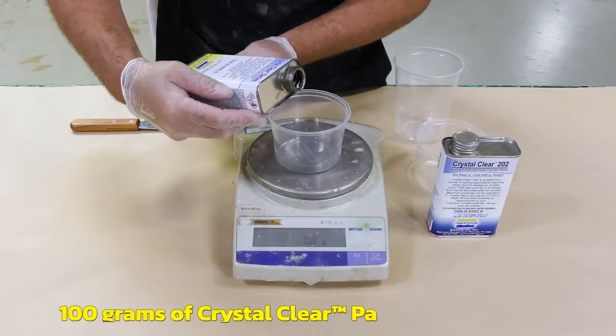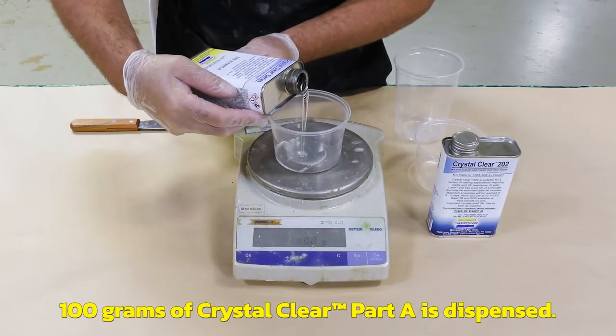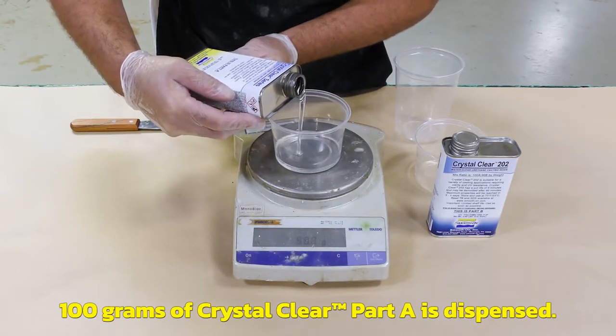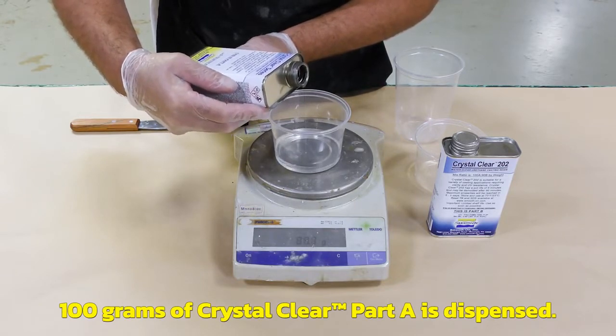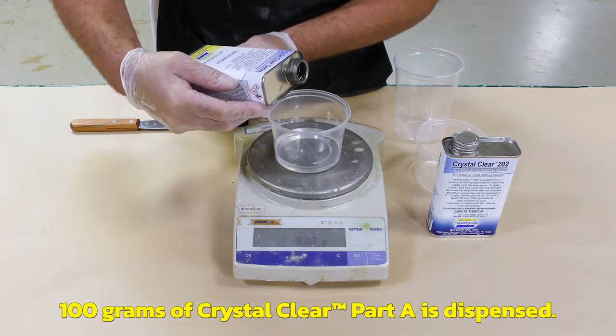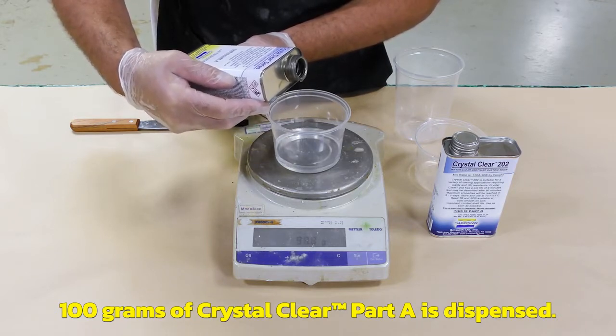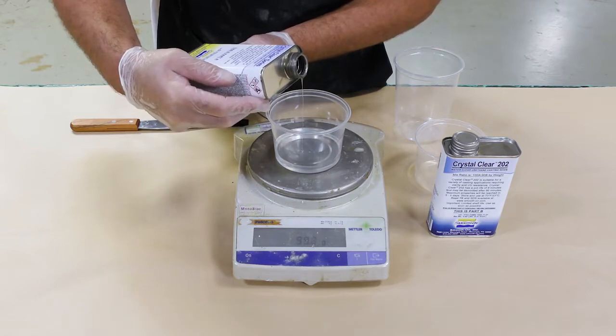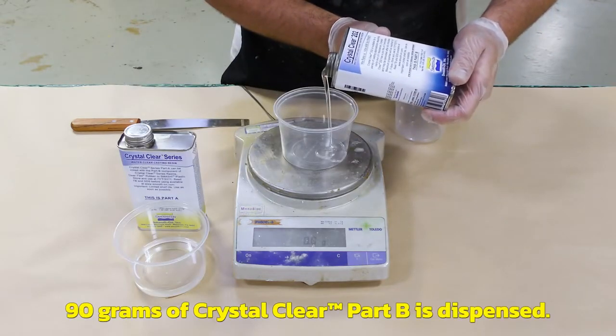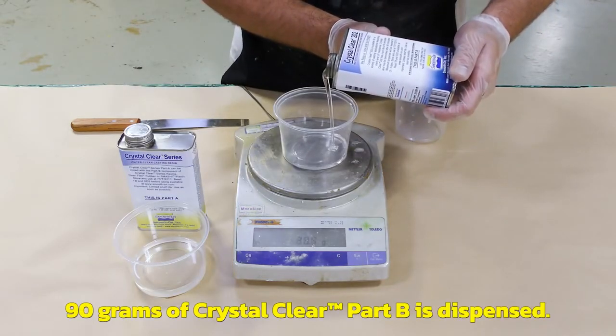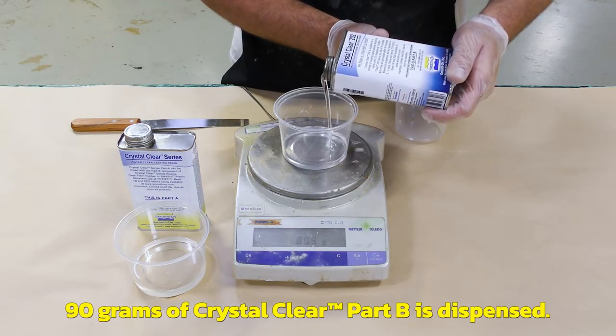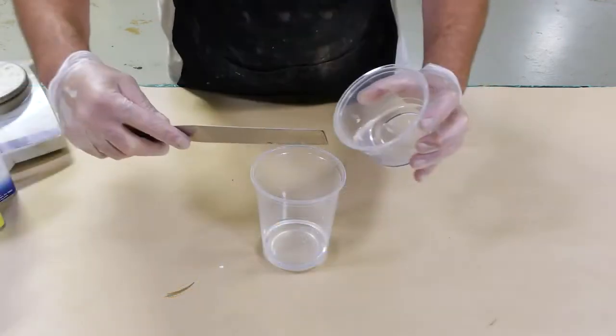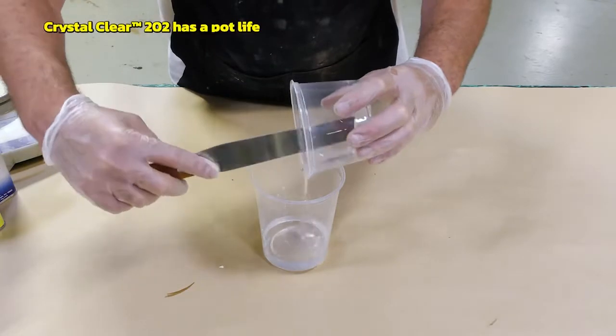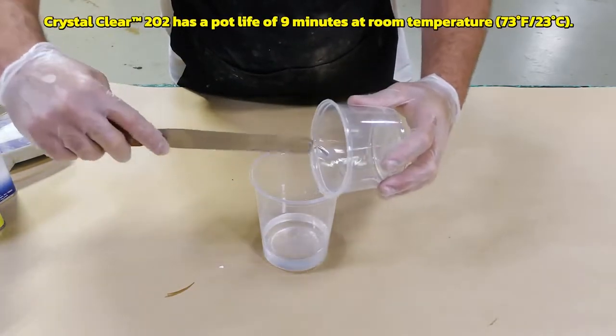Because the material is a by-weight mix ratio, we do need to use an accurate gram scale. I'm going to stick to the formula for the mix ratio and dispense 100 grams of the part A, and then dispense 90 grams of the part B. I'm going to combine the two components in a clean mixing container, and keep in mind the working time is